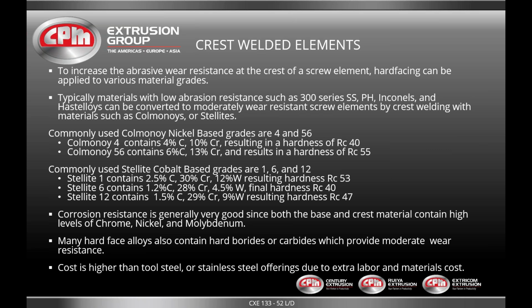With crest welded elements, to increase the wear resistance of some of the low wear resistant austenitic, pH, or superalloys, hard facing can be applied to the crest or the flight tips. Most materials with low abrasive wear resistance, such as 300 series stainless, precipitation hardening grades, Inconels and Hastelloys, can be converted to achieve a moderate degree of wear resistance by crest welding with materials like Colmonoy or Stellite products.